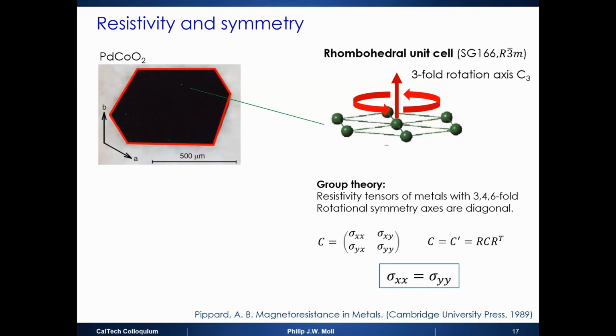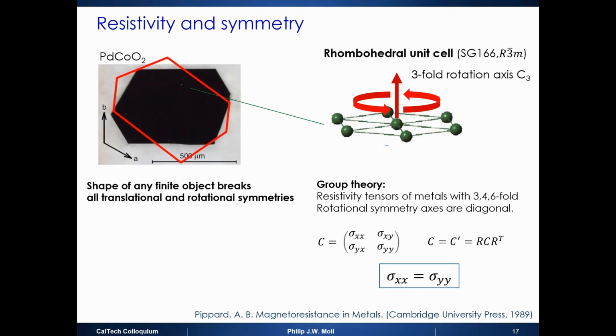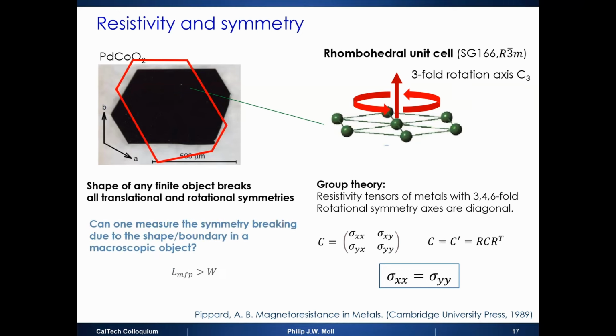But it's of course not quite true, because we don't live in that infinitely sized crystal. In reality, the macroscopic shape of this object will not be rotationally symmetric. This crystal, clearly you rotate it, doesn't overlap. The point group does, but the crystal does not, which is an effect that usually you don't see, because surface scattering terms are not really relevant as compared to bulk scattering terms. But if you make this object small enough, maybe you can start to see this.